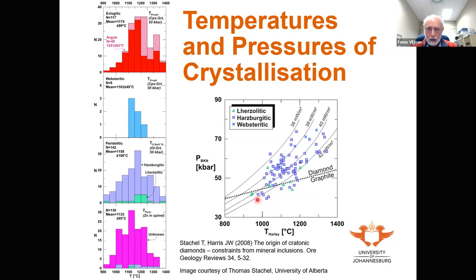This is the graphite stable field. There are uncertainties with regards to the temperatures and pressures that you can calculate, which is the error bar. But for the most part, our diamonds plot in this region in the diamond stability field, and they sit at comparatively low geothermal gradients. These are geothermal gradients, which is essentially the heat flow through the lithosphere. Within thick lithosphere, the heat flow is comparatively low because the lithosphere is thick and serves as essentially a thermal insulator from the hot asthenosphere. And so at geothermal gradients on the order of about 38 to 40 milliwatts per square meter at surface, you have the right type of conditions for diamond to crystallize.